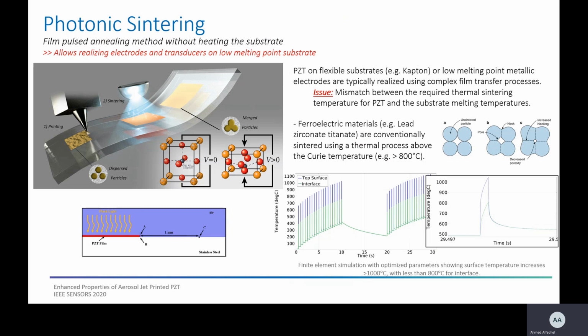By definition, sintering is a high-temperature process that is used to densify PZT powder in order to enhance the electric and mechanical properties. Conventionally, PZT is sintered at temperatures larger than 1000 degrees Celsius and for a duration longer than 1 hour. This exceeds the melting point of commonly used electrode materials and, of course, flexible plastic substrates.